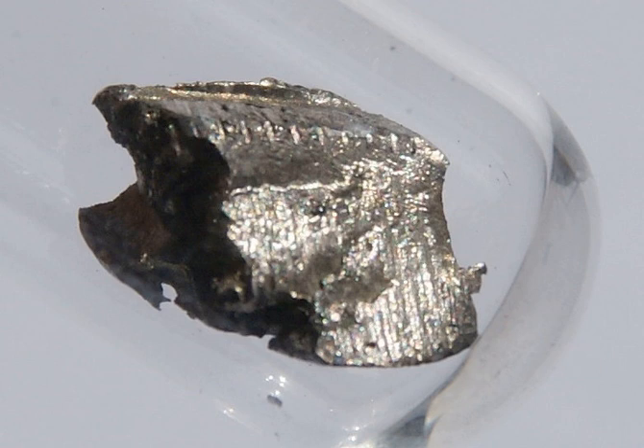Aqueous cerium(IV) is metastable in water and is a strong oxidizing agent that oxidizes hydrochloric acid to give chlorine gas. For example, ceric ammonium nitrate is a common oxidizing agent in organic chemistry, releasing organic ligands from metal carbonyls. In the Belousov-Zhabotinsky reaction, cerium oscillates between the +4 and +3 oxidation states to catalyze the reaction. Cerium(IV) salts, especially cerium(IV) sulfate, are often used as standard reagents for volumetric analysis in cerimetric titrations.